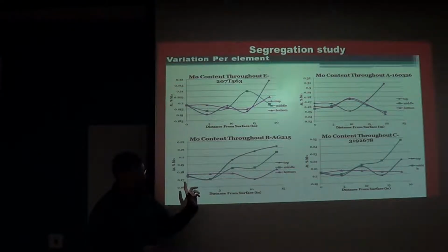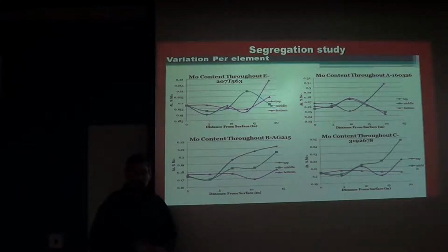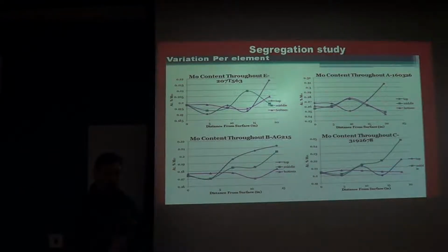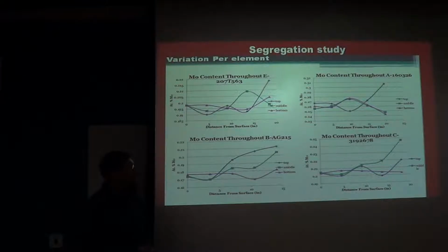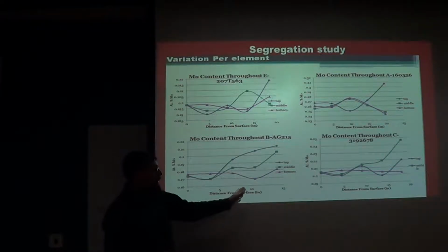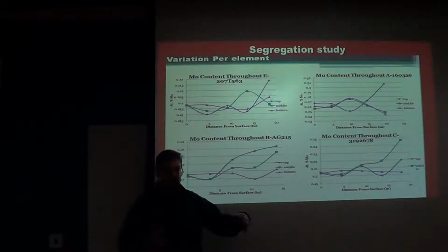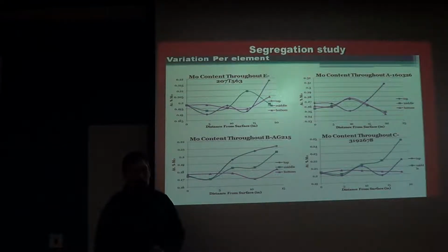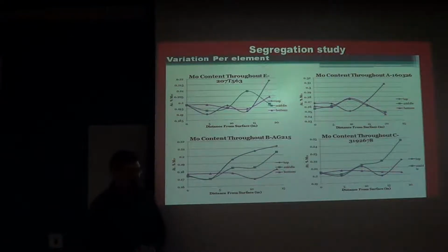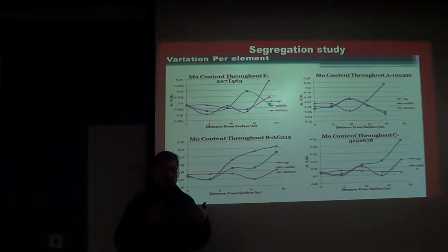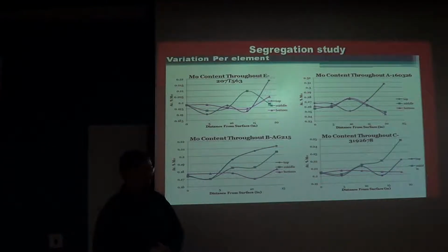When you look at carbon, you see even more dramatic behavior because carbon is a much smaller atomic radius. It's a lot easier for it to move around. So this is quite significant because if I'm making a finished forging and then I'm going to be checking the mechanical properties, do I check out near the surface? Do I check in the center? Do I check somewhere in between? That's all going to make a difference, or at least have the potential to make a difference to the results that I get and how well I do at meeting my customers' expectations.